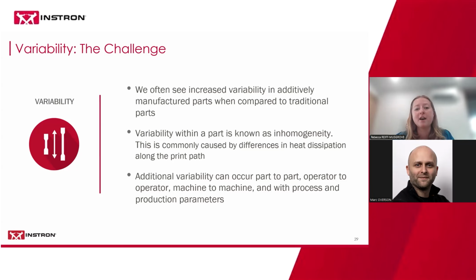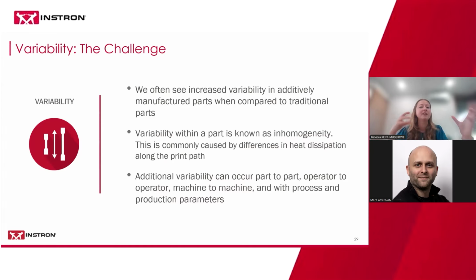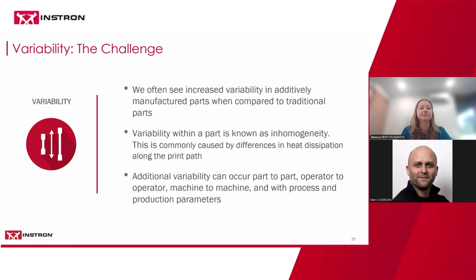So if you imagine a very thick area of the material, it will take longer for that heat to dissipate compared to a very thin part of the same print. And you get differences in heat dissipation, you get differences in material properties within the part. But it doesn't stop there. We also get variability part to part, maybe due to the different parameters or print path, operator to operator, machine to machine in terms of the additive printer, and also with different process or production parameters, we get variability. So as you can see, there are a lot of different sources of variability, both within and across parts.